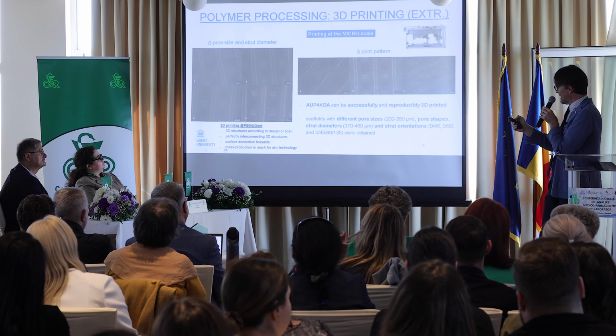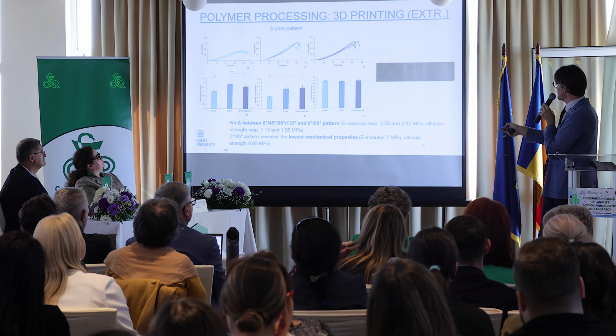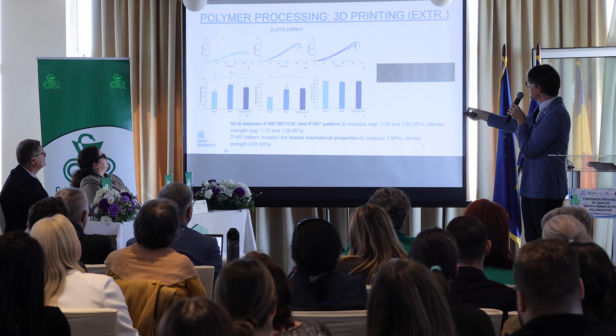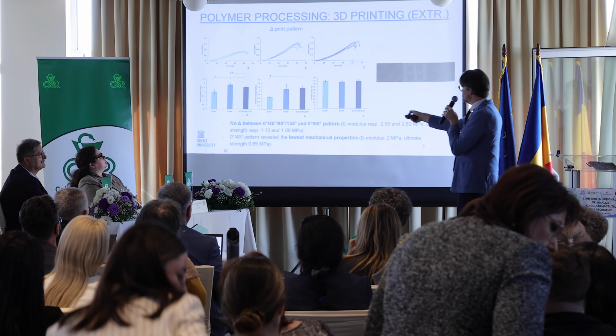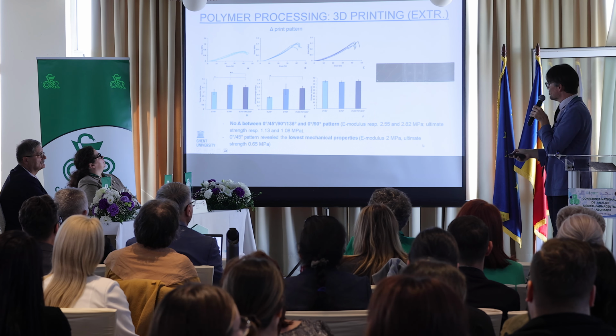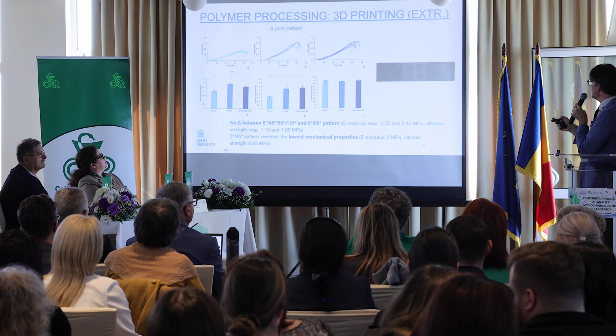So different architectures were being produced, and of course then for us it was important to see what effect that had on the mechanical properties. And I will just focus here on the graph on the left. You can see that one printing pattern has a certain mechanical property, Young's modulus of 2 megapascal, and if you change the printing pattern, you increase or decrease your mechanical properties. The main conclusion was the fact that only those two patterns come close enough to the mechanical properties of the human meniscus to really apply it in the long run. So that already reduced the number of samples. So this pattern was skipped from all further tests, and those two patterns actually survived the first stage.